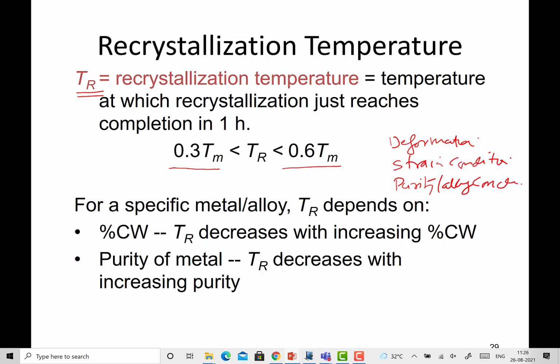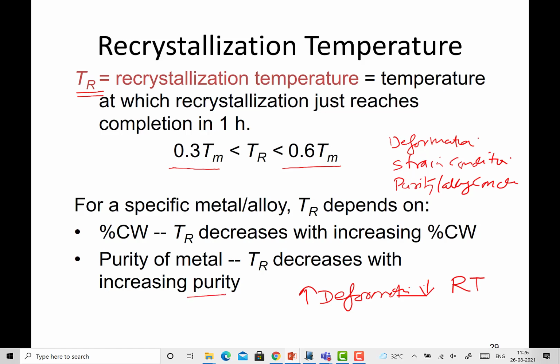So if you see this aspect in general, increasing deformation reduces the recrystallization temperature, RT. And the second is that increasing purity decreases the recrystallization temperature, which means with the increase of alloying, there may be a marginal increase in the RT. So these are the two different aspects.